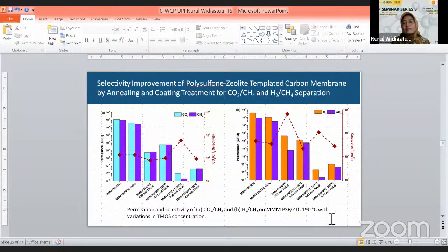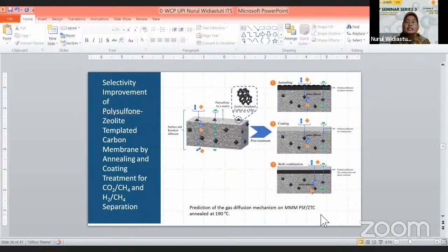And this is the permeation and selectivity of gas pairs of CO2 and methane, and also hydrogen and methane, on the mixed matrix membrane polysulfone and ZTC at 190 degrees Celsius with variation in TMOS concentration. TMOS is tetramethyl orthosilicate that we use as a coating agent for the membranes. And here's the illustration of the prediction of the gas diffusion mechanism.